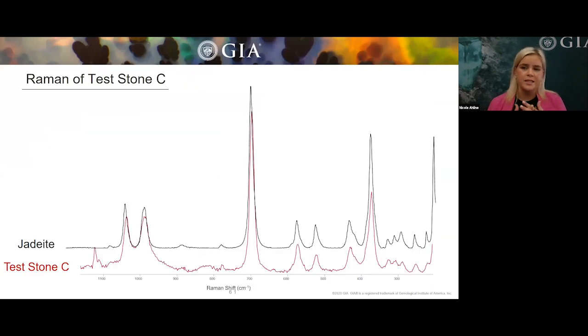So since we are unable to get that refractive index, we will want to run a Raman on it. And you can see the black is our reference Raman, and then that test stone C, that maroon one, is actually our stone. When we run the Raman and overlay it with a known spectrum, our pierced carving ends up to be jadeite. We know that it's not dyed because we got nice chrome bands, but now we got to check for polymers.